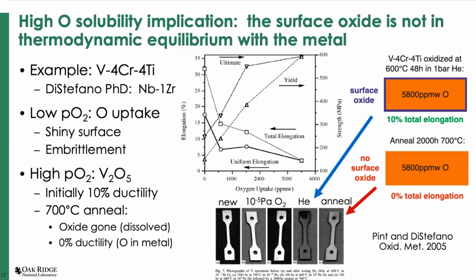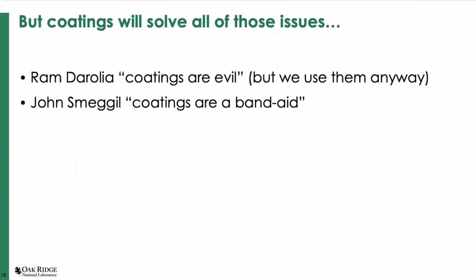And so the oxygen went into the alloy, and now we can test that, because again, we're doing it all on tensile specimens. And now we have no ductility anymore, because now we get 5,800 parts per million oxygen in the alloy. And a relatively shiny specimen, once again. Not quite as shiny as it started, but we don't have the clear oxide formation on the surface. And you can see that publication that we had back in 2005.